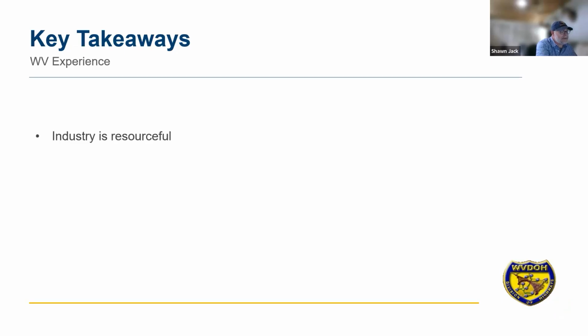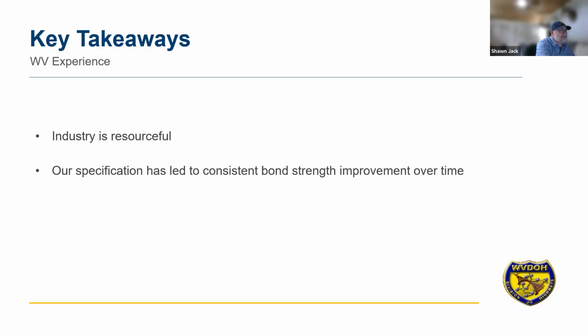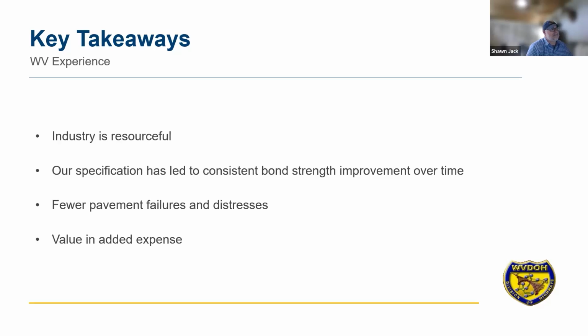Also, industry is resourceful. If you give them an end result specification, they'll rise to the occasion and find a way to make it work, to perform better work, and it'll just improve exponentially over time. So our specification has led to consistent bond strength improvement over time, which we showed on the bar graphs. We've seen fewer failures and distresses, a lot fewer, I should add. And lastly, I want to drive home that there is an added cost to this bond strength specification, but we believe there's significant value in that added cost.